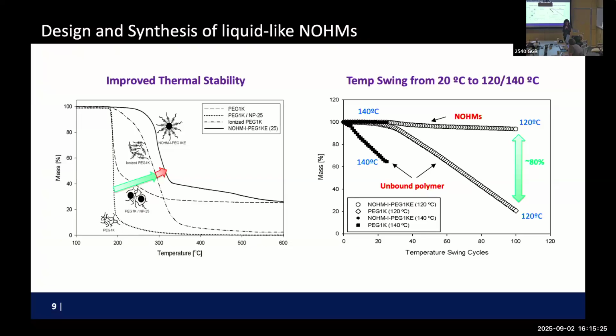So one of the reasons I found out was that in the liquid we made, we tried to remove the water as much as possible because it's supposed to be a water-free liquid solvent. And then what we found out was that 3 to 5 weight percent of water you cannot ever get rid of. You can pull a lot of vacuum, you can heat it up, it was stuck, it won't come out. So then I'm like, okay, this is dead weight, water weight, I need to carry around back and forth in different reactors.